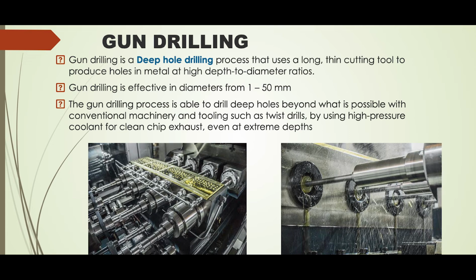For instance, drilling a 20 mm axial hole through a heavy 30 mm diameter shaft makes the shaft much lighter while maintaining its stiffness. This lighter shaft has less rotational inertia, which in turn reduces energy consumption. The image and slide show a process where 2 to 3 gear shafts are gun drilled at the same time to long depth. The gun drilling process is able to drill deep holes beyond what is possible with conventional machines and tooling such as twist drills, by using high pressure coolants for clean chips even at extreme depth.